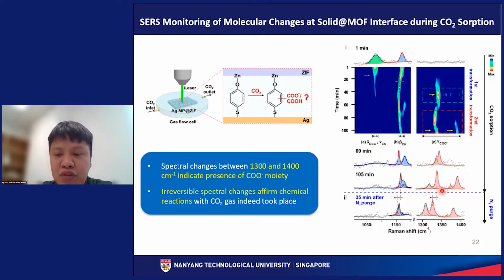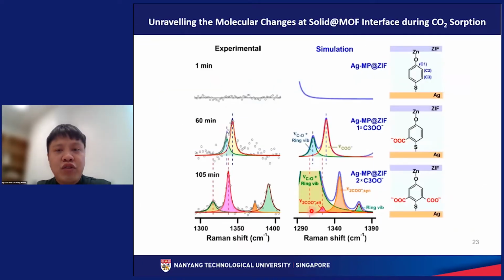Upon subsequent purging, we can see that there is a red shift, but the peaks are still over here. So the presence of a permanent peak in the range of 1,300 to 1,400 wavenumber clearly tells us that chemical reactions with carbon dioxide indeed took place in our system. So next, we try to compare our experimental results with our DFT simulated results to unravel the molecular changes at the solid@MOF interface during CO2 absorption.